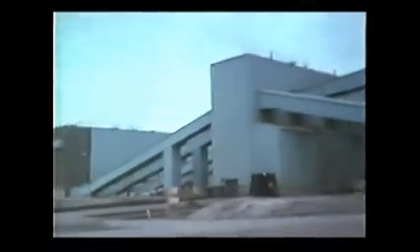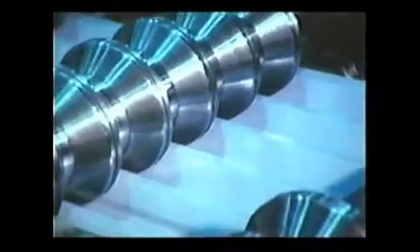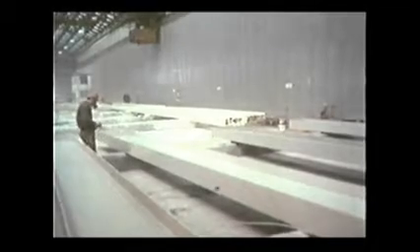Over galvanized steel, this paint looks good after 10 years, and it will probably still look good after 15 or more. They call it a synergistic effect. The combined effect of galvanizing and painting is greater than the sum of both effects taken separately. Structural steel can benefit from this same synergistic effect through the use of paints specially formulated for galvanized surfaces.